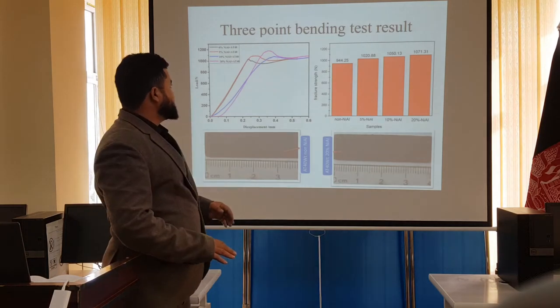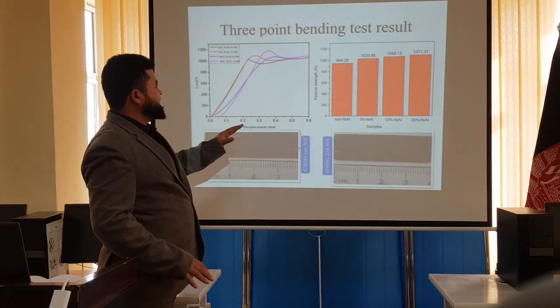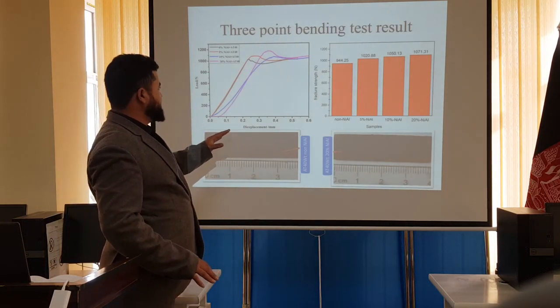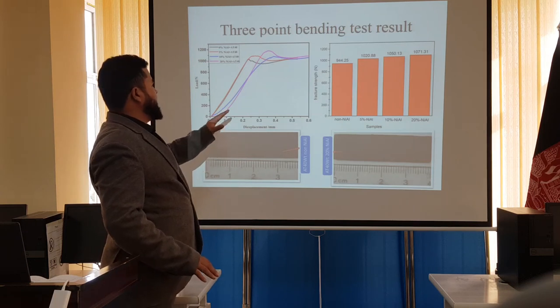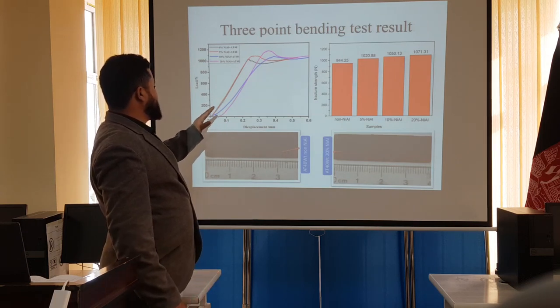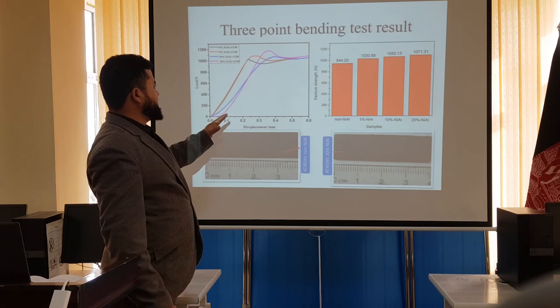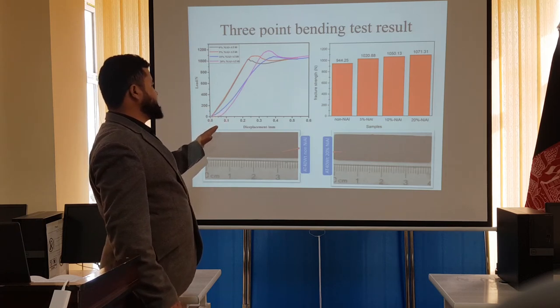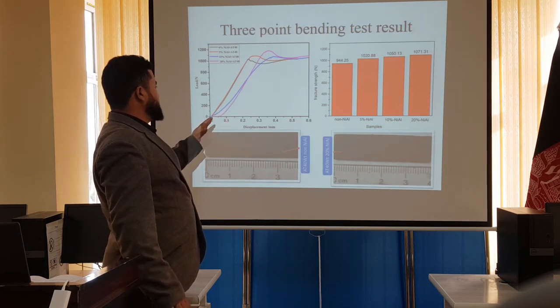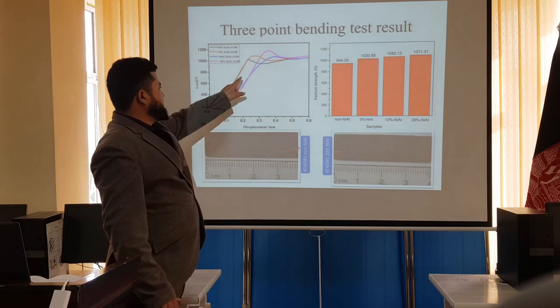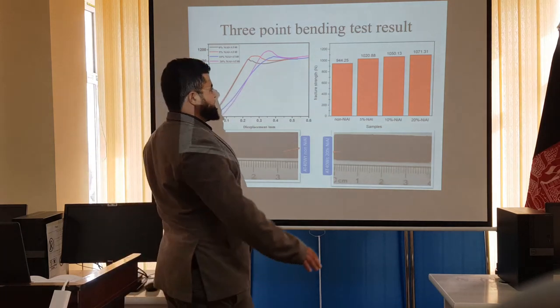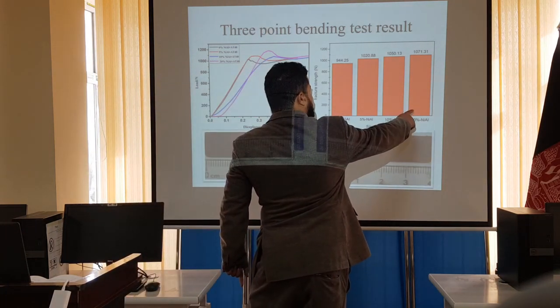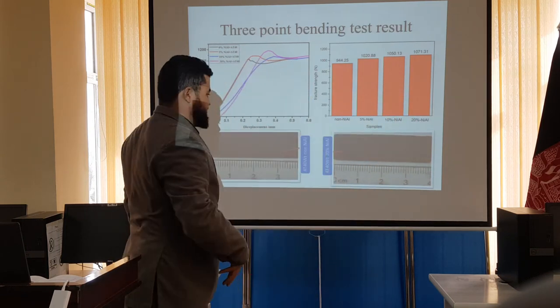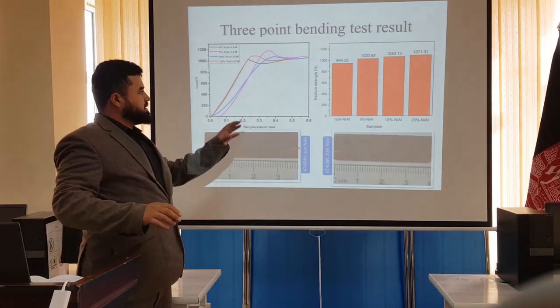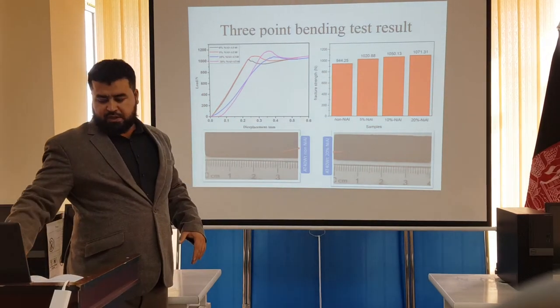The other test we did was the 3-point bending test. After the 3-point bending test, we found that by doping 20% nickel aluminum in the 8040 ceramic coating, fracture toughness increases, and we can see the result directly here. With 20% nickel aluminum doping, we can see clearly that fracture toughness also increases. We also analyzed this result theoretically, by equation.